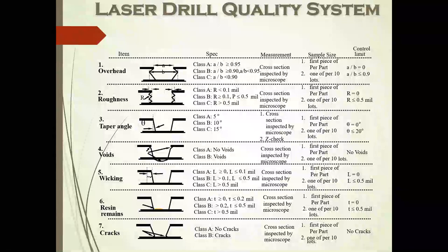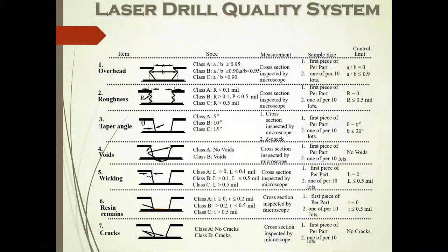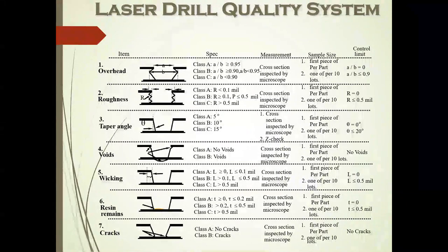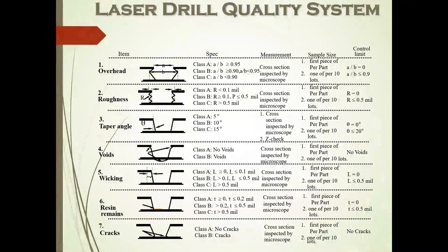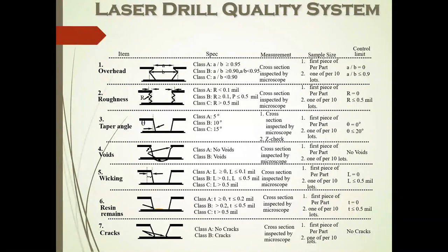When you're dealing with laser, laser drilling is a lot more complex than mechanical drilling through holes are. One of the things we developed and used is a seven-item check on the quality of laser drilling. That's because you can't set up the drilling parameters like you would for FR4 or normal through hole boards. Every customer has a unique stack up, unique selection of materials, and unique thicknesses, so you have to do test runs and optimization of the stack up and the design rules that a particular customer has selected.